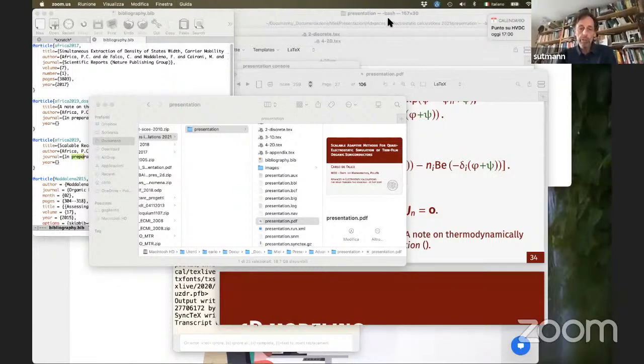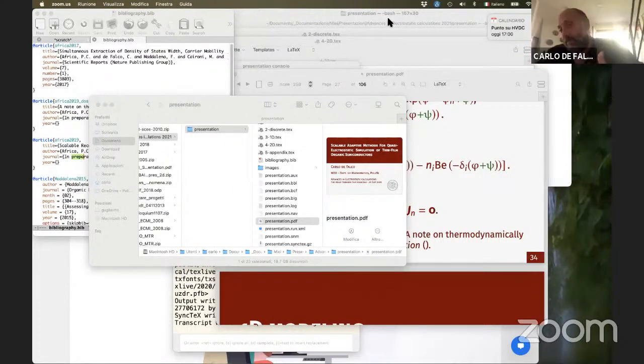How would you estimate the overhead for the repartitioning afterwards? We measured that in our case to be less than 1%. The time needed for partitioning is always less than 1% of the total simulation time. Okay, thank you. And that's for the repartitioning. The repartitioning is unmeasurably fast, and that includes the remeshing. But also in this case, it's not complicated, so it's expected to be fast.